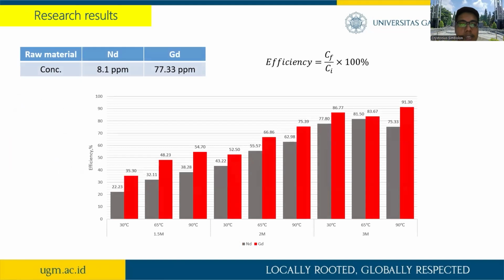Next, research result. This is the result of ICP analysis of the raw material for concentration of neodymium. We got 8.1 ppm, and then the gadolinium concentration 77.33 ppm. For calculating the efficiency of leaching at all variables we use CF per CI multiplied by 100%. That means CI is the initial concentration, and CF is the final concentration after leaching.